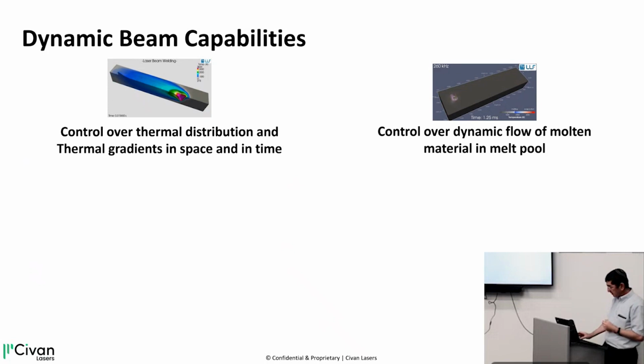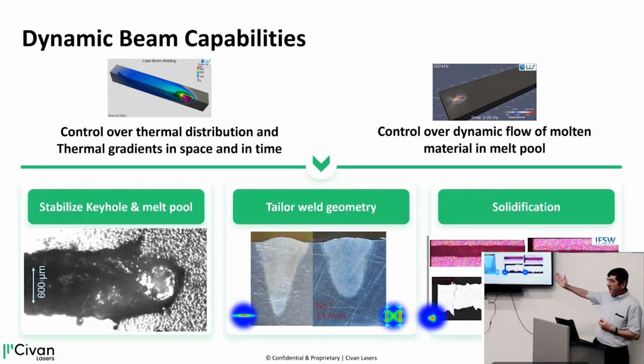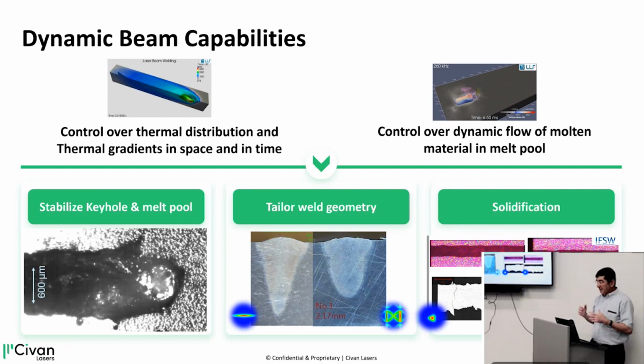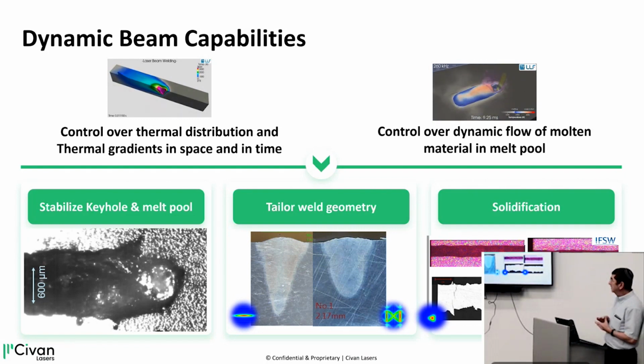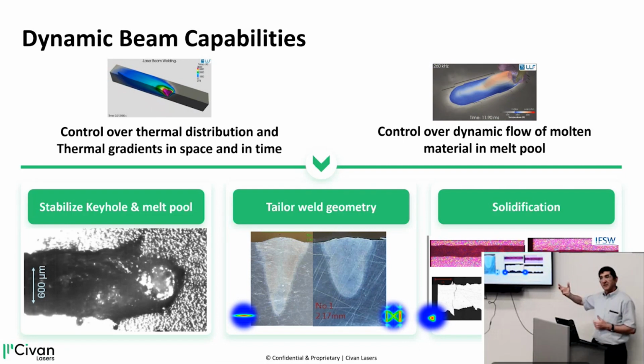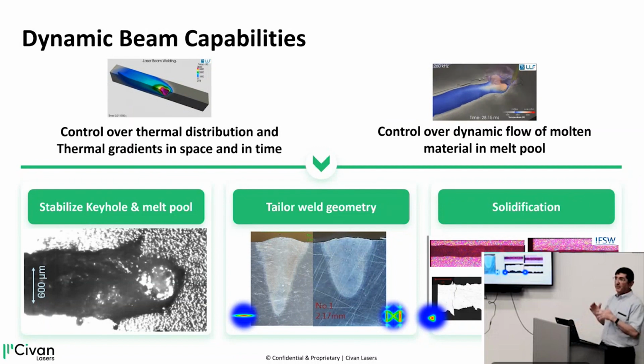This is completely revolutionary, and it allows us to, first of all, stabilize the process, tailor the geometry of the weld, and control the resolidification process, thereby avoiding cracks, porosity, spatter, humping, and controlling the phase of the metal to what it resolidifies to. Okay, so this is really differentiating from anything that exists today, and that's why we can do welds today that nobody else can do, and therefore, instead of traditional welding or brazing or electron beam welding, we can do it with a laser with all the advantages.